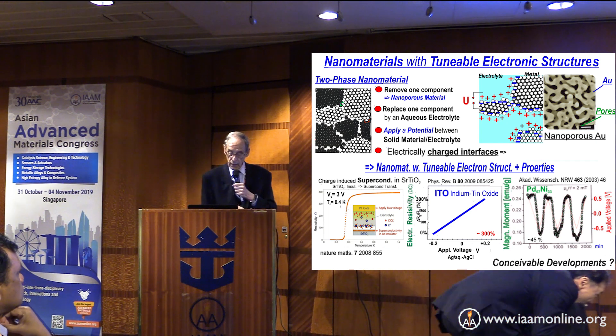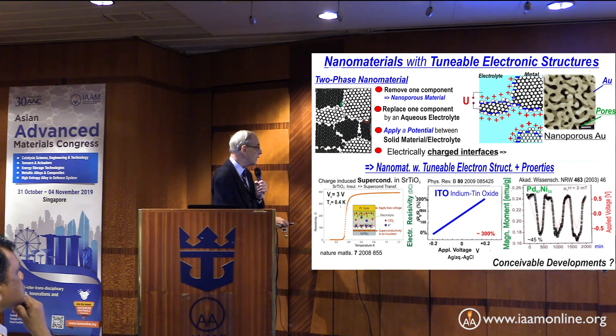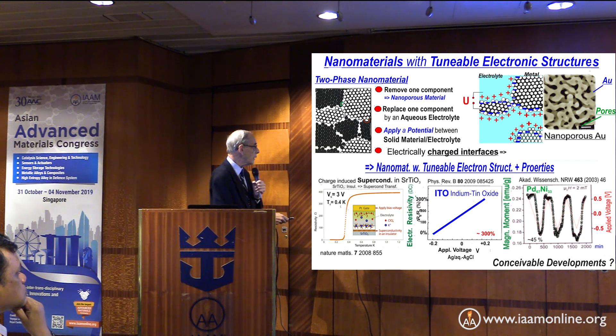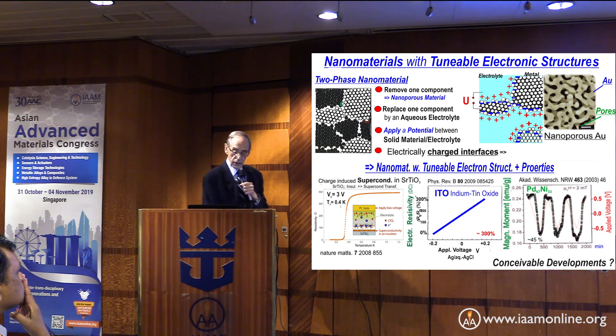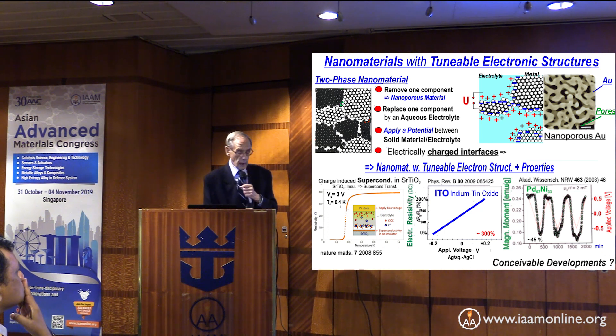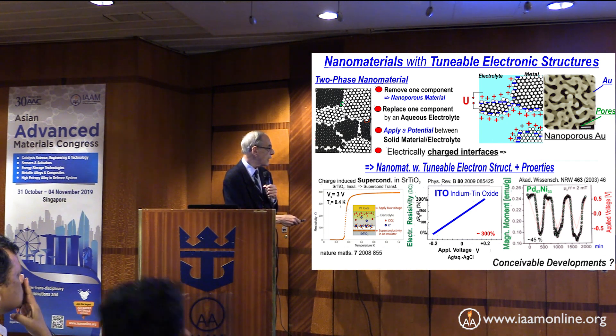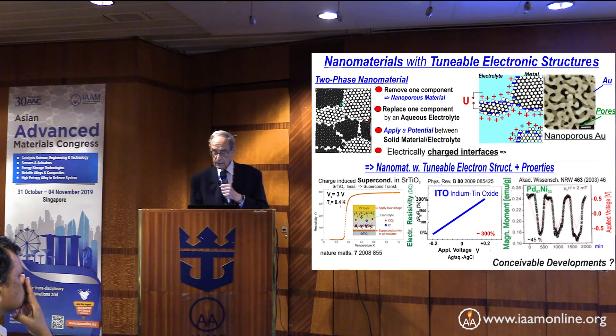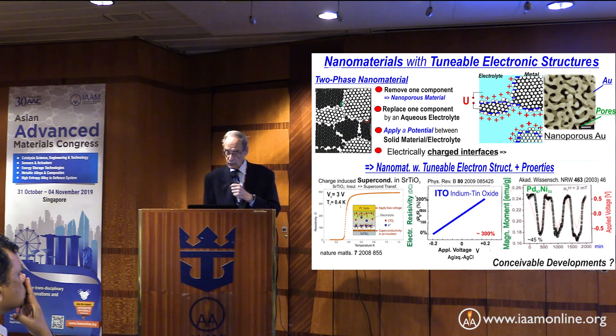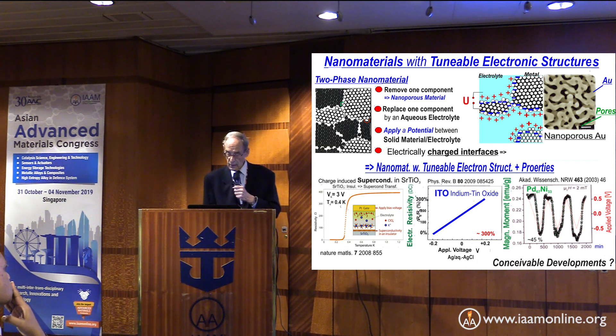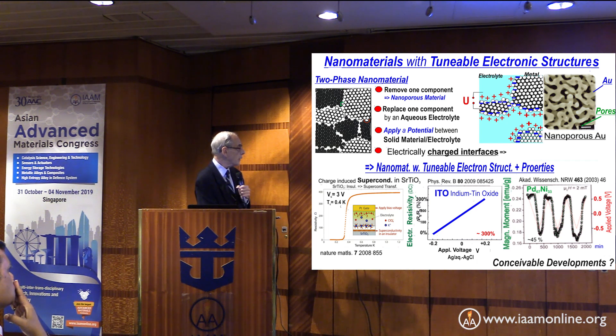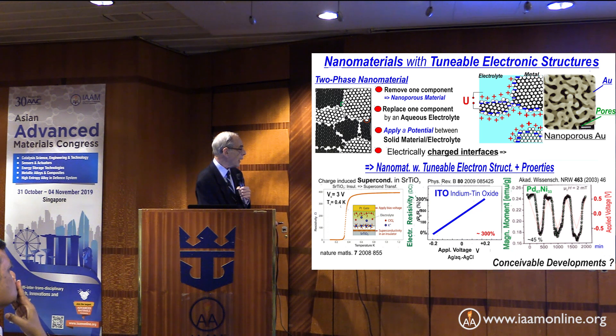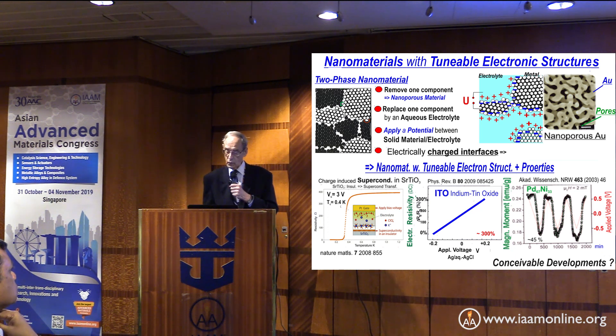Another property is shown on the right side: for a different material, when we charge it, we can change the resistivity by about 300%. And on the right side here, the magnetic moment of a palladium-nickel nanoglass — by applying voltages of about half a volt, we can change the magnetic moment by about 45%.